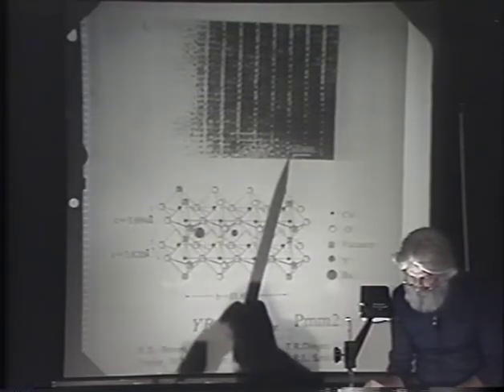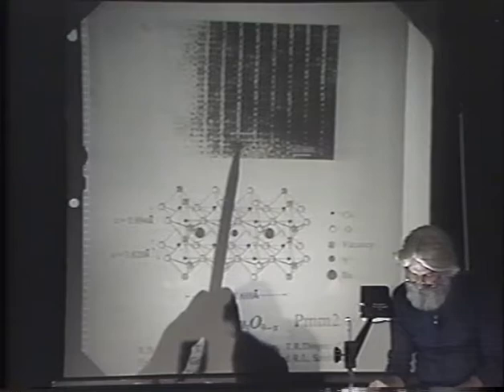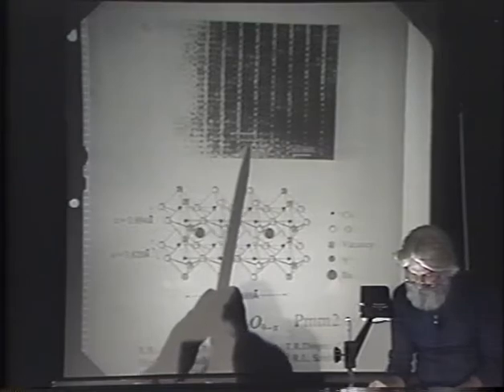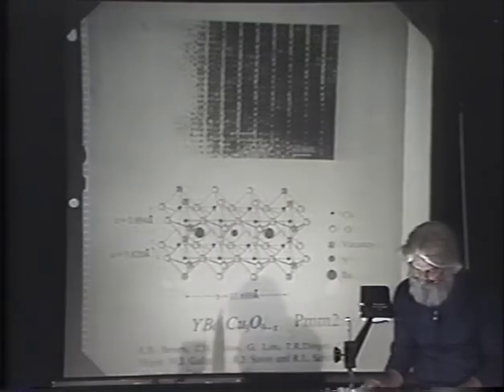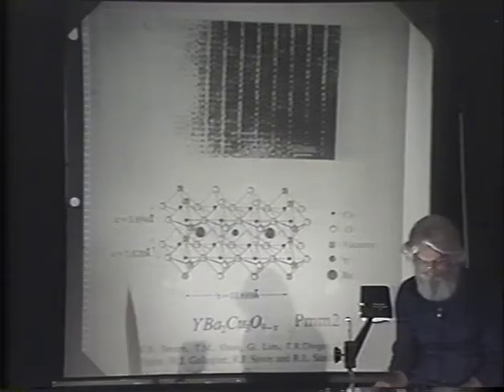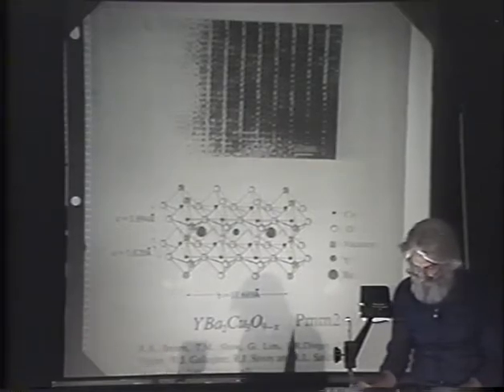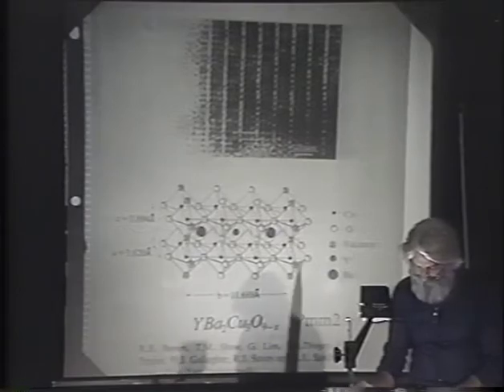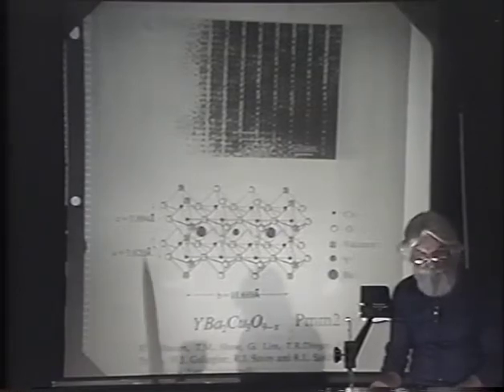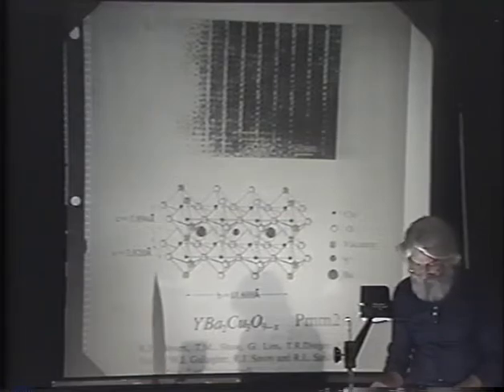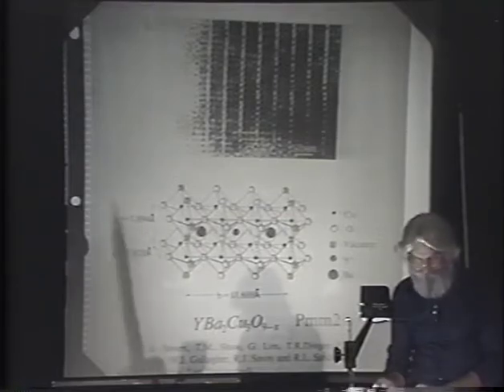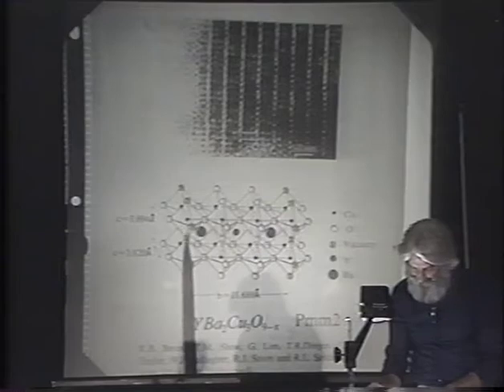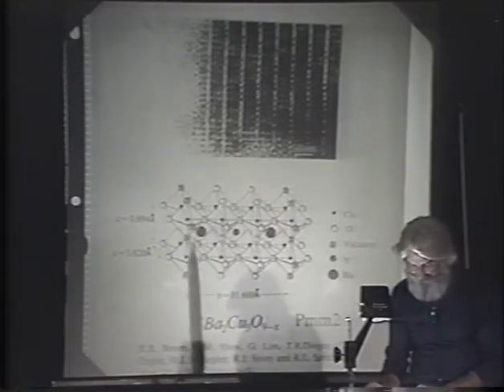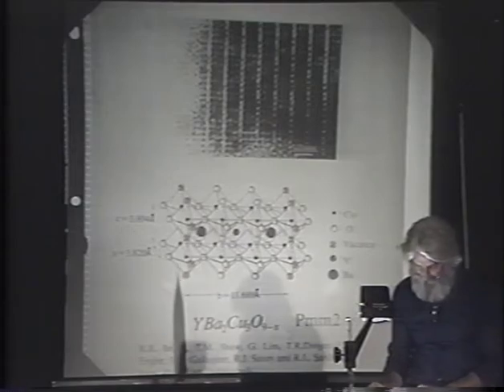Here we're on a 12 angstrom scale. Clearly you see the barium, yttrium, barium ordering. Convergent beam definitely shows the loss of a mirror plane. The space group is PMM2. We have put the cell horizontally in conjunction with standard crystallographic notation of having the C-axis along the two-fold axis. So there's some small distortion in this direction of the yttrium and the barium. How much, we don't know.